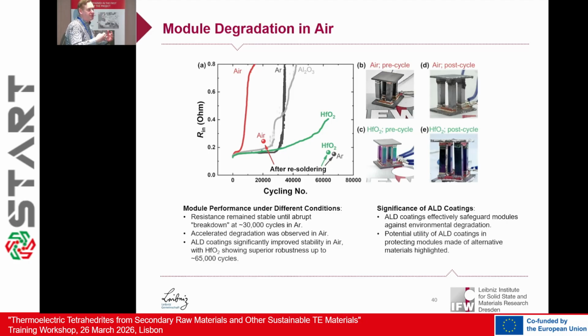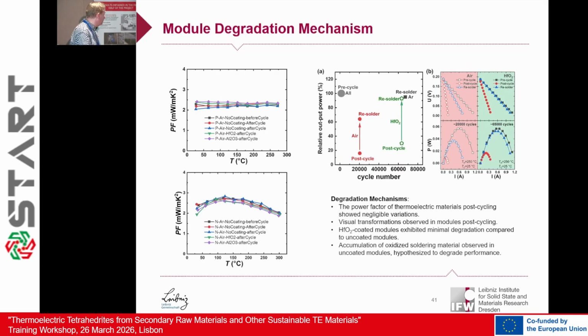If we unsolder the module and resolder it again, we come back to the same performance we had from the beginning. So the weakest point where we have to do some optimization is the soldering material, to find a better way to thermostabilize this module. For all the cooling applications in this temperature regime, you're usually heating up maximum 100 degrees or so, so you don't have to do it.